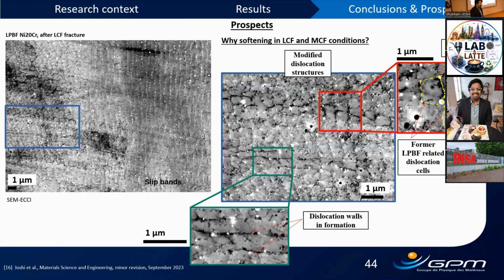I thought you made a bet. I have put $100 on the table with 50% of the yield stress. I do the test. I'm sure I will have fatigue failure at some stage, which means that I've got irreversibility, starting at very, very low stress levels. If you give time for the process to set up, you will have some, but it is a very long, very high cycle test. And the thresholds are, I think, very low.